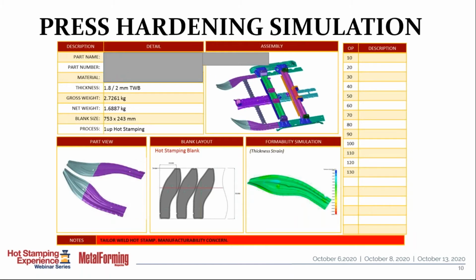The first step in evaluating a process is simulation. And as was brought up earlier, the press hardening simulation is complicated because you are dealing with a number of different variables. Unlike cold stamping, where you're primarily dealing with the material, surfaces, geometry, and friction, in hot stamping, we have a lot of other variables involved.